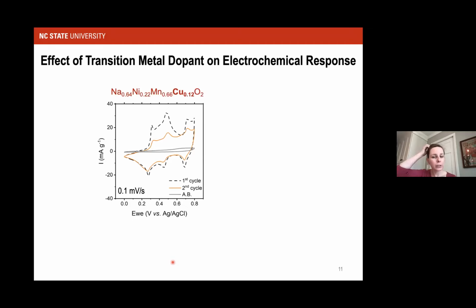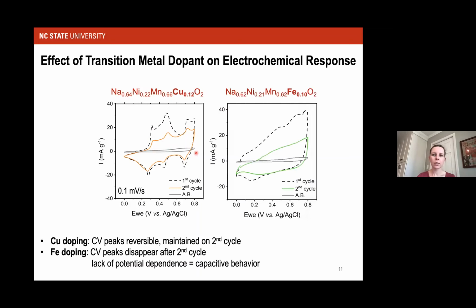What happened when we then started to do some electrochemical cycling? So we placed these into a sodium sulfate aqueous electrolyte. If we took those same copper materials, our cyclic voltammograms in terms of capacity weren't perfectly reversible, but in terms of the redox peaks, you could see they were very clear and they were reversible on multiple cycles. So the dashed line is the first cycle and the solid orange line is the second cycle. The gray here is indicative of the acetylene black, which is present as a conductive additive.